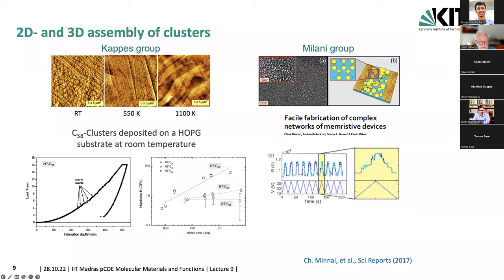But what you also see is that there are special events occurring here, which are called pop-ins, which we typically know also from other materials, from glasses, etc., when you form shear bands. So this is an abrupt initiation of a deformation process which extends over a large distance, and this results in these pop-ins in the load indentation depth curve. The authors in this collaboration also found a very high hardness in gigapascal, and depending on how you deposit and post-process the material, you can get different hardness values, which are plotted here as a function of the strain rate.